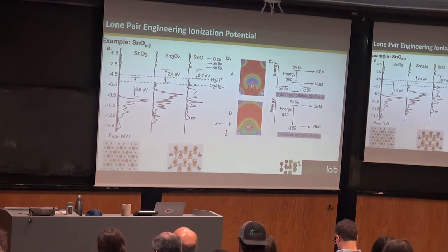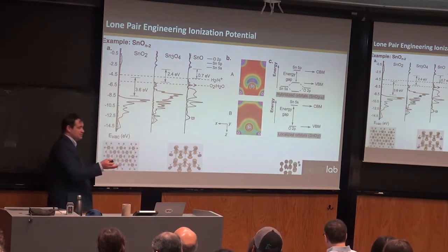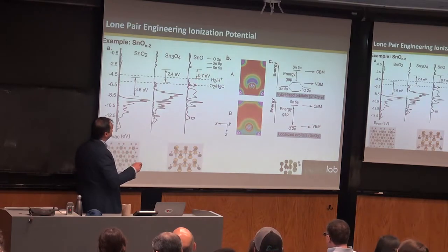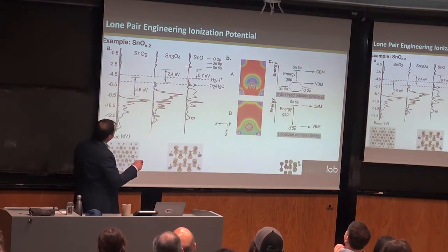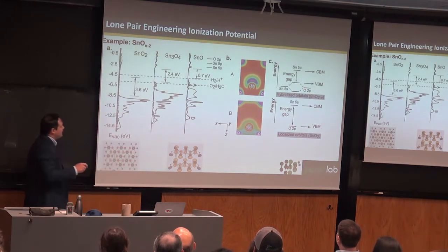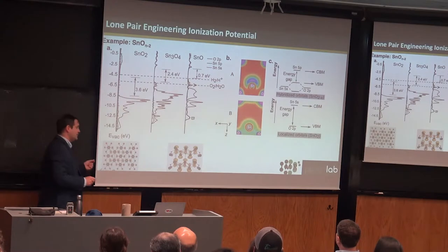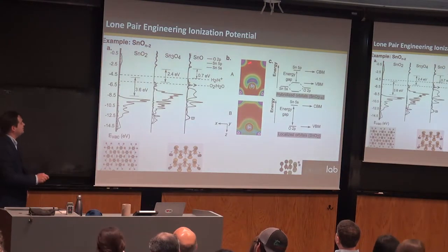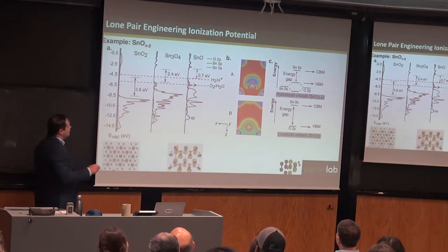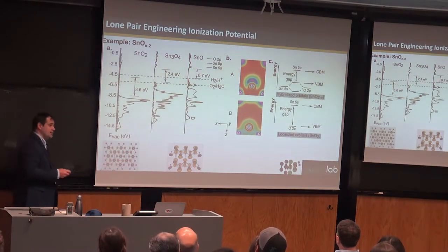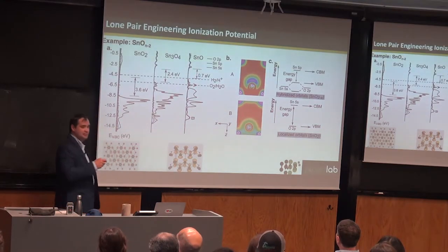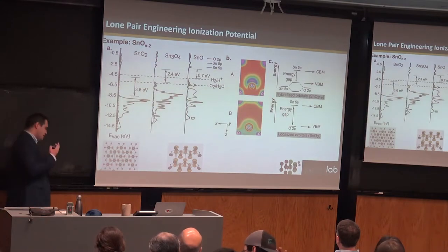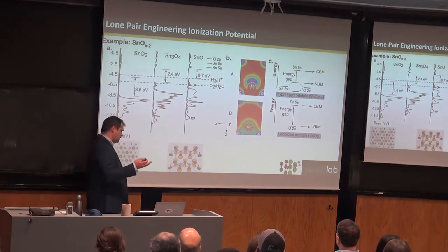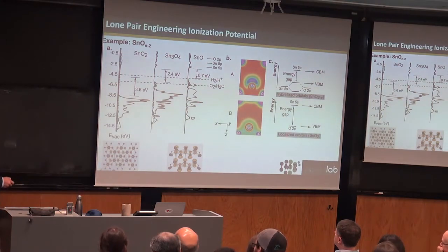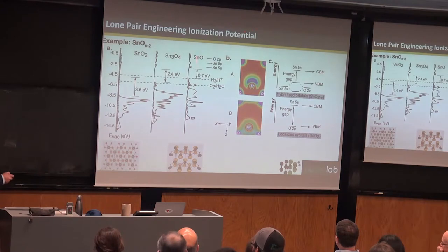But the cool thing about tin monoxide is if you look at it, it actually looks reasonably transparent, orangey. And the reason for that is it has an indirect band gap. And so this small band gap between the band edges means that to a certain extent, it behaves like a narrow band gap semiconductor, which is quite good. Narrow band gap oxide semiconductor, which is good for your electronics, and meanwhile, optically, it does look transparent. And so you can actually drive this system to be both N-type and P-type, which is quite cool. Because then you can make invisible metal oxide semiconductor transistors, or you could move towards invisible logic with this approach. But for the purposes of the water splitting, it's not so great.